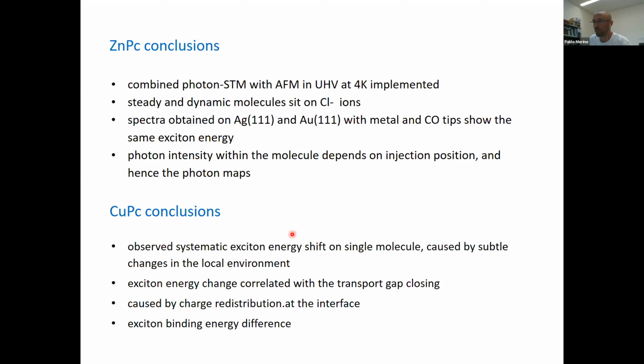On the copper, on the contrary, we see that there is a systematic energy shift caused by subtle changes in the local environment, and this is correlated to the transport gap closing, and we were able to measure the exciton binding energy difference between both states.